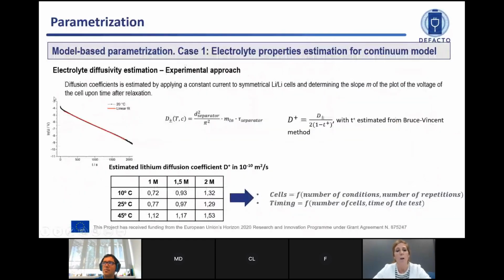So here we are now focusing on the electrolyte diffusivity estimation. From the experimental approach, as I said, we have to assemble lithium-lithium symmetrical cells, and then perform galvanostatic pulse relaxation. From the relaxation, if we plot the logarithm of the voltage, and then get the slope of this figure, we can then get the diffusivity. But for that, we need the transport number, for which we would rely on the Bruce-Vincent method. So this is quite tedious, and as we know, the electrolyte diffusion coefficients depend on the salt concentration and on the temperature.